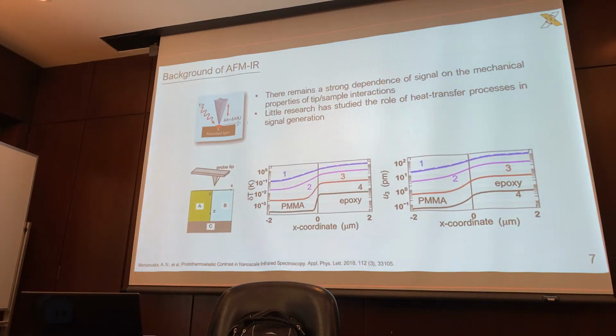So based on this, there's still a strong dependence of the AFMIR signal on the mechanical properties of the tip and sample interactions. So that's one of the downsides of AFMIR. For instance, in the case of some samples that Sonia gave me, they responded so strongly to the infrared signal that I was literally degrading the sample. So we have to come up with a new technique to measure those. And as I said before, little research has been done on the role of heat transfer processes in signal generation.